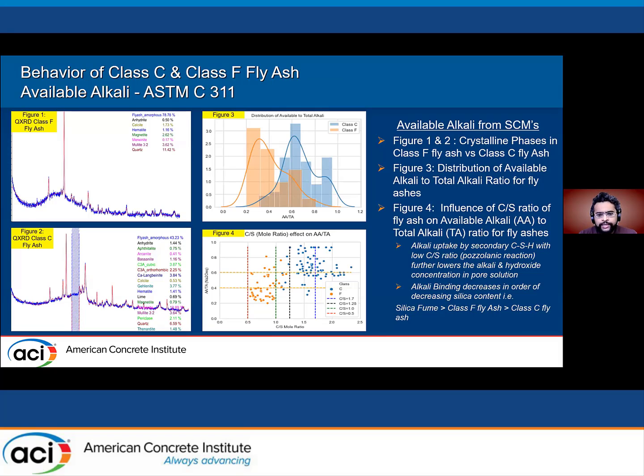So why is the composition really important, and why do we have to consider it for deciding the behavior of these ashes? This is the QXRD quantification of both class F and class C fly ash. As we saw on the previous slide, the contribution of the alkali directly comes from the crystalline phases, and for class C, we see a significantly higher level of alkali crystalline phases compared to class F fly ash. This is directly reflected in figure 3, where on the x-axis, the available alkali to total alkali ratio for class F is significantly lower than class C. What is important to notice here is that we see two distinct peaks, as in there is a definite distinct level of alkali contribution from F and C ash just based on composition.